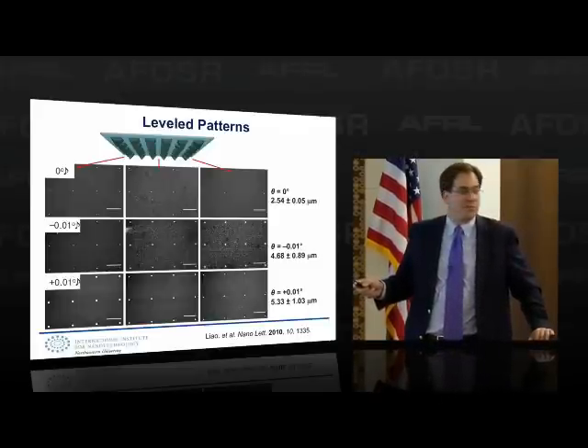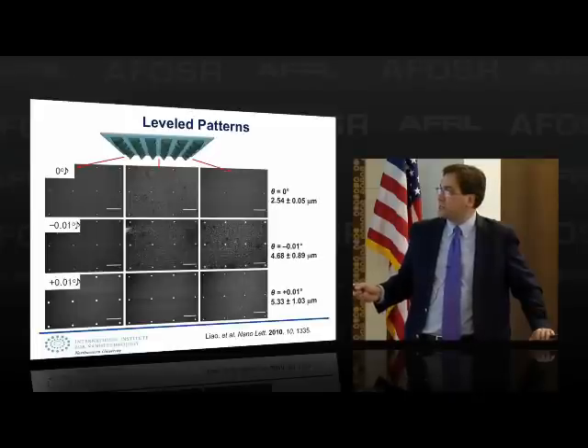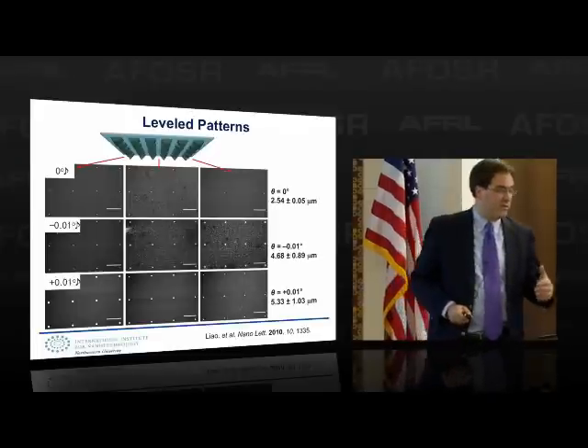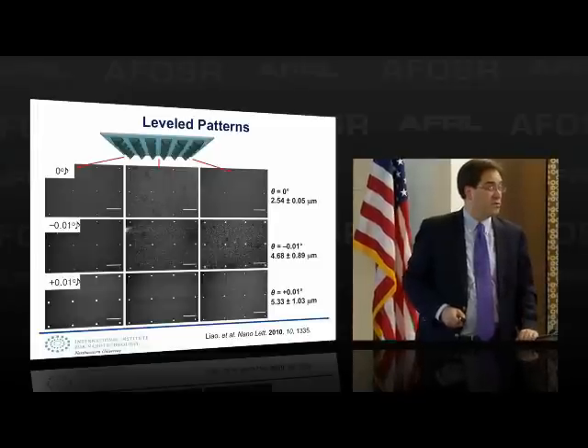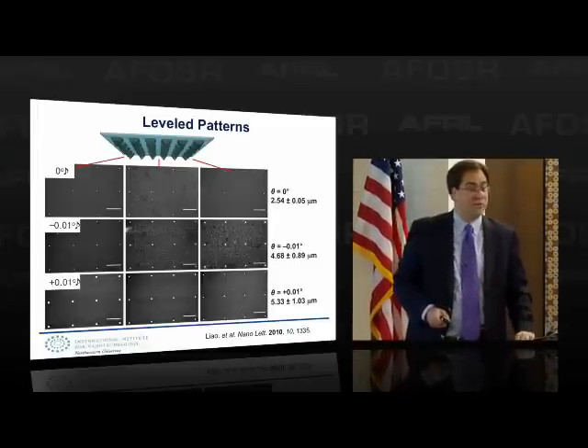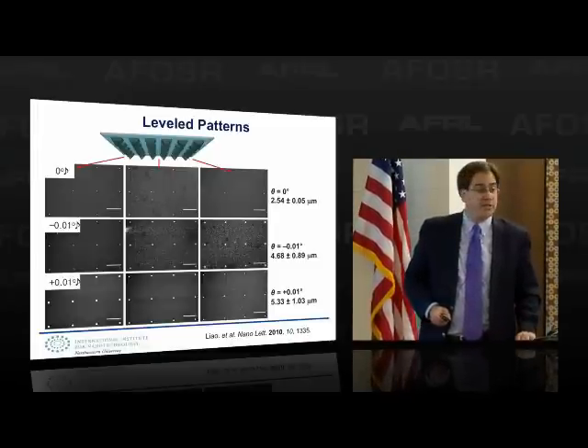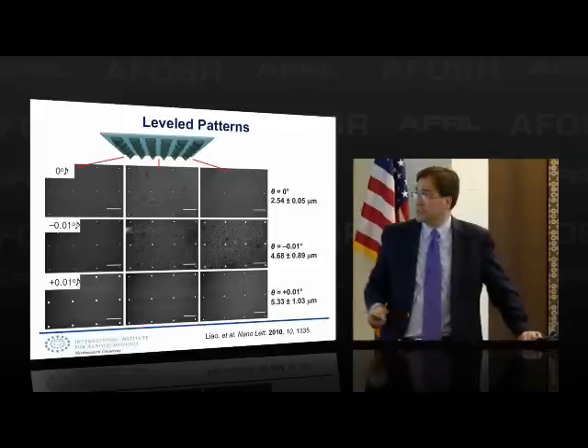There are 15,000 pyramids in here, 1 square centimeter, leftmost side, middle, and right. You can see the feature size. It's effectively, the variation is as good as you're going to get with any sort of lithography when you take into account roughness of the substrate. There's no significant variation in feature size.